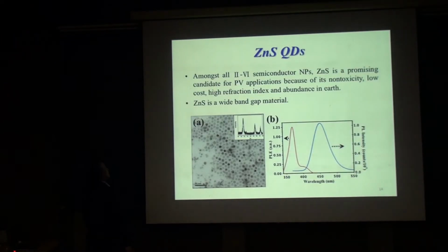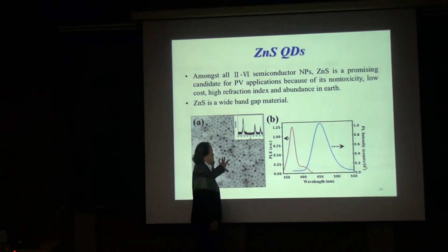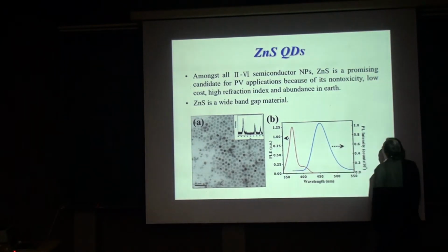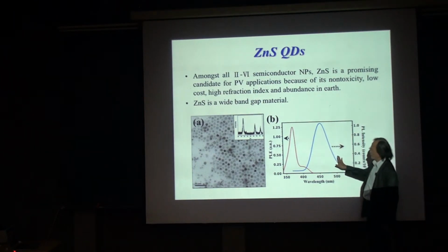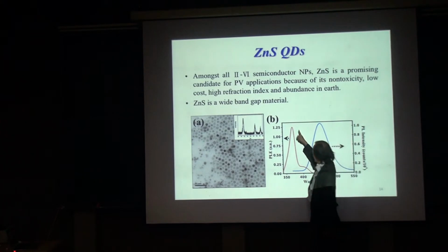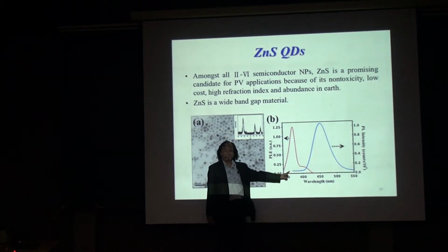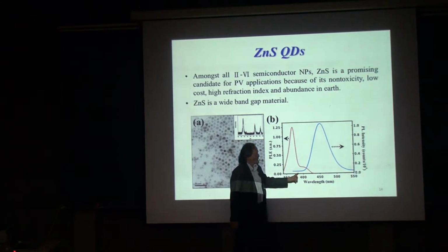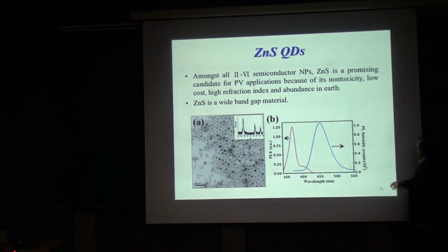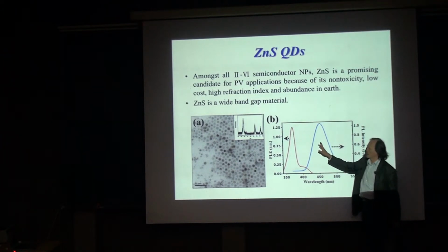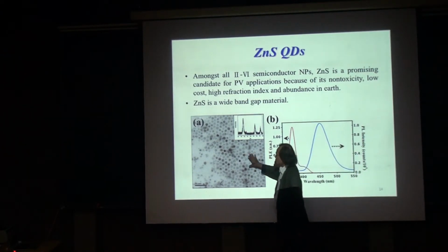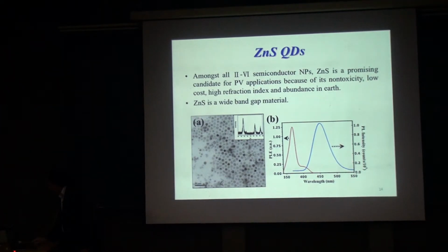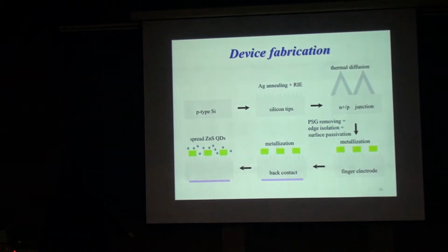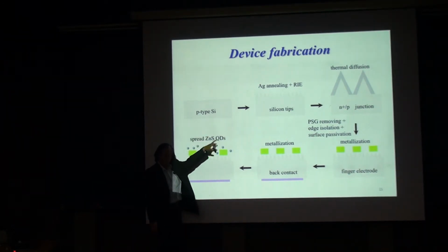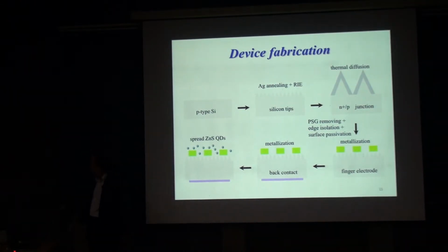Yes, we do have it. This is a zinc sulfide quantum dot. This is the TEM image, and this is the absorption spectrum and the emission spectrum. You see, this is the absorption peak near the UV region, and the big emission spectrum is in the visible region. So this is very different. So we have this kind of system. So if we deposit this kind of semiconductor on top of the solar cell, and I'm not going to go into the detail of how to fabricate the solar cell device.